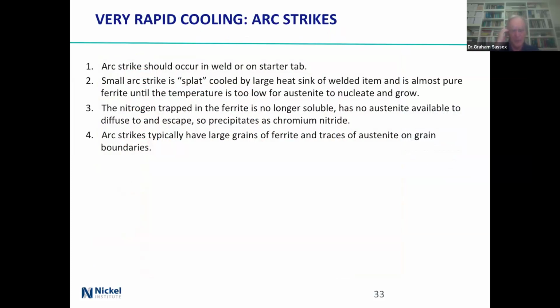Okay, what about rapid cooling? Rapid cooling, the obvious place is arc strikes. Well, arc strikes never happen on the surface, do they? They always happen in the weld or on a starter tab. I hear hollow laughter through the ether. If you've got a small arc strike, it's basically a splat cooled on a very large heat sink, and it's almost pure ferrite. And so it'll cool down until it's too low for the austenite to nucleate and grow. And what happens to the nitrogen that was in the ferrite?